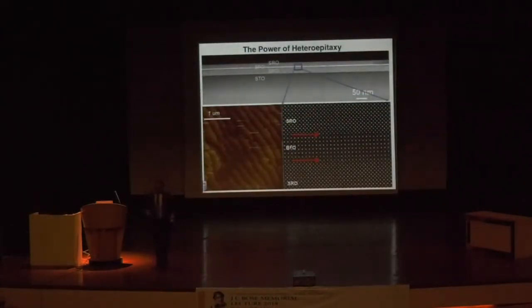Basically, we now have the ability to grow materials with atomic scale precision. And this is just an example of this material. There are 6 unit cells of bismuth iron oxide here, and you can basically follow them one atom at a time. You can put down these things either by regular MBE systems or by laser MBE and grow them with 2 angstrom precision. That's half of the unit cell of the perovskite structure. And that's basically what this TEM shows you.